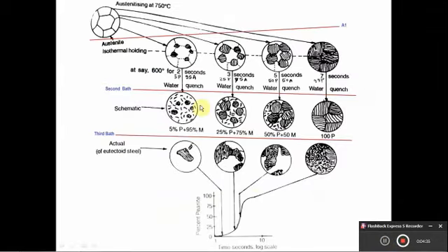So here, schematically, the microstructure will show how the transformation will begin. This red line indicates the A1 temperature, meaning all the samples which are kept in the A bath will show a complete 100% austenitic structure. Then this second red line indicates the second bath furnace which is maintained at 600 or 700 degrees Celsius, that is, at subcritical temperatures. And this third red line indicates the third bath, which is the water quenching bath, at room temperature.